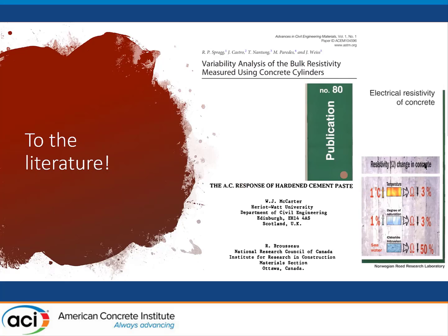And so when we look at this publication in 1995 from Norway, we see that they actually discuss different coupling methods, including using metal meshes and brass meshes, embedded, not embedded, and so forth. And they settled on using a conductive graphite paint, if you will, to act as the coupling mechanism for the electrode. And that seemed to work really well.